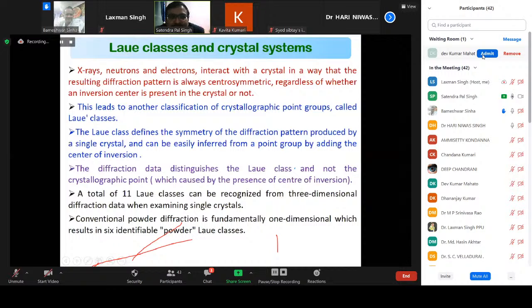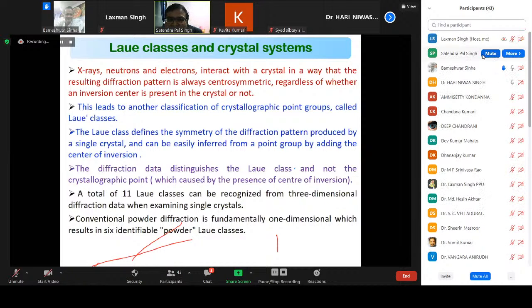Besides the point group, people are also confused with the Laue class. As we know, X-rays, neutrons, and electrons interact with the crystal in such a way that the resulting diffraction pattern is always centrosymmetric, regardless of whether an inversion center is present or not. If we have an electron diffraction pattern, it is very clear to explain: if we have a 1, 1, 1 plane, then there is always a -1, -1, -1 plane, or 1 bar, 1 bar, 1 bar plane. So there is always a center of symmetry.